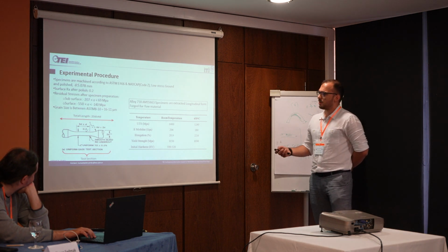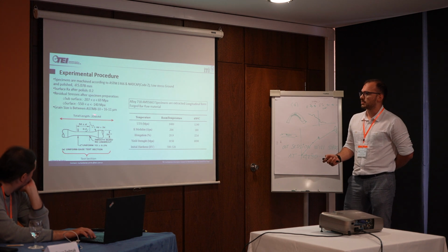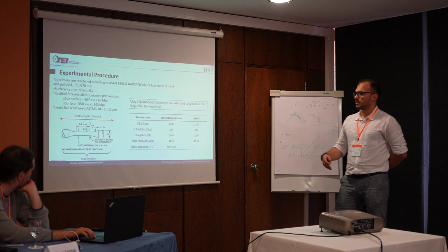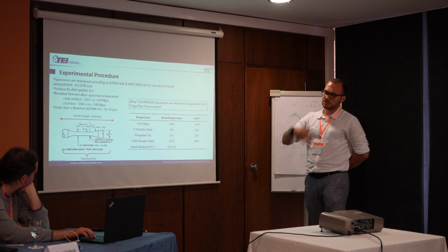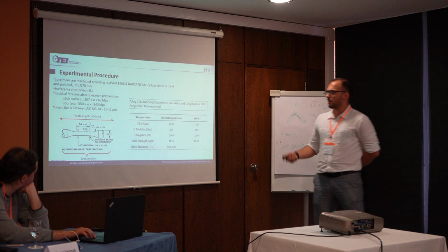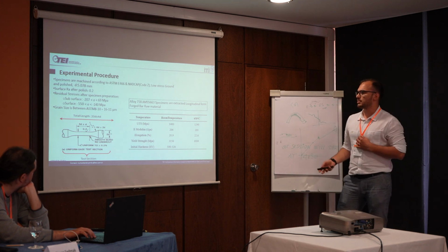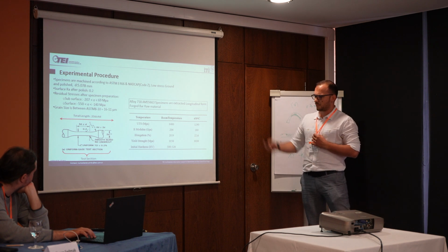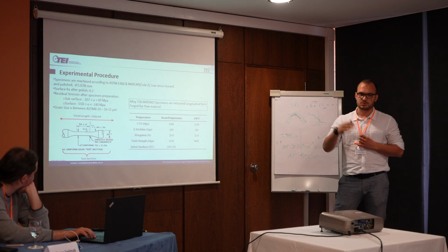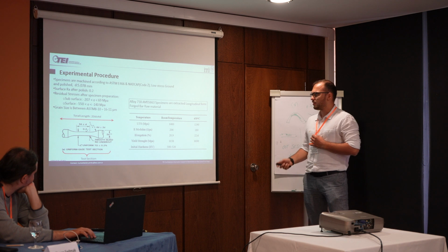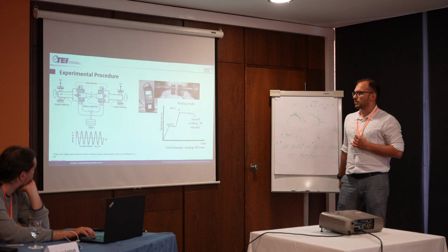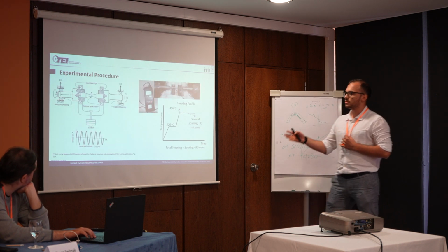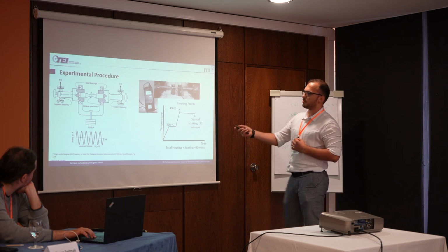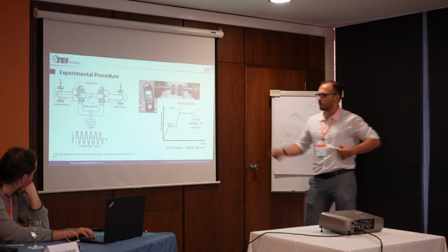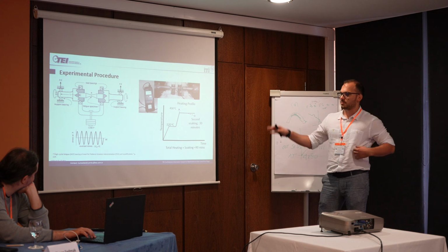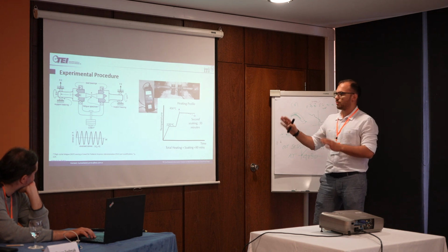We also measured the grain size before starting and after the tests, just to see if there is a change or not. Our initial grain size is ASTM 8 to 10, about 16 to 11 micrometers per grain. We can move on again. So we did our tests, as I mentioned before, with rotating bending. Here, I would like to present some of the testing part of our work.